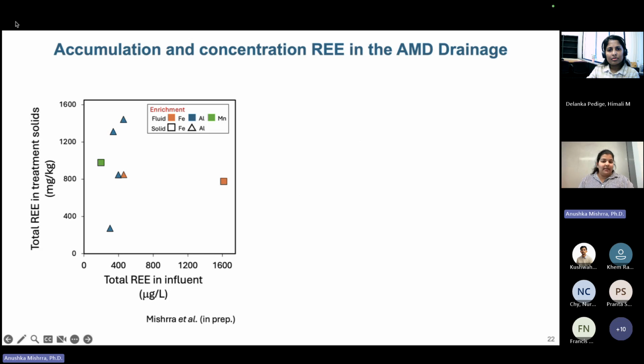So going back to the same data that I showed you previously, the other important aspect of this plot is that I have grouped these data points based on how the fluid and the solids are enriched. So you can see that all the blue triangles are basically solids and fluids that have high concentrations of aluminum, whereas the orange points actually have high concentrations of iron in it. And there's one point that we have that is rich in manganese in the fluid.